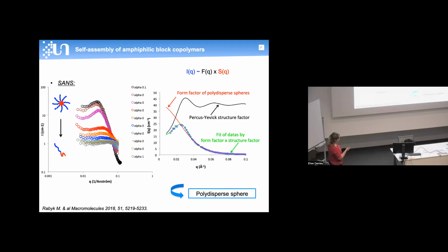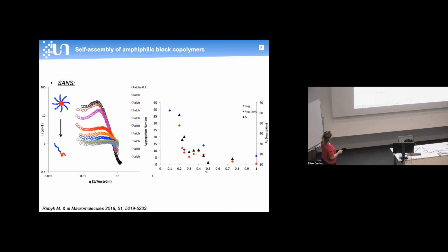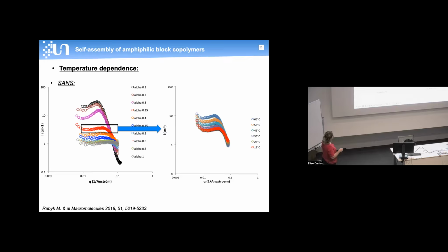So we could quantify the SANS result by applying a model of form factor of polydispersed sphere and a structure factor of a percus-yevick to get aggregation number and core radius of the aggregate. And we get aggregation-disaggregation behavior like what we got in light scattering, with a critical range of ionization degree alpha between 0.2 and 0.5.